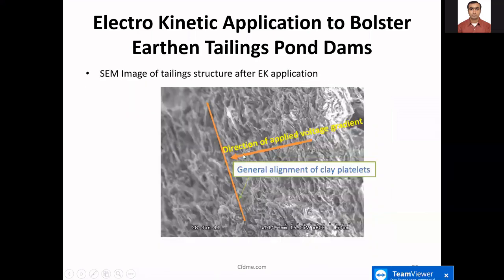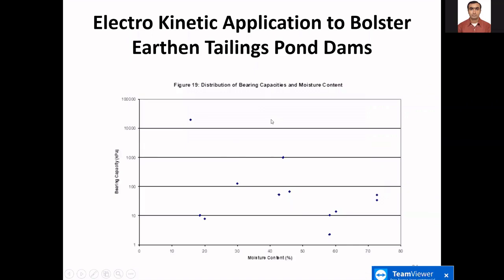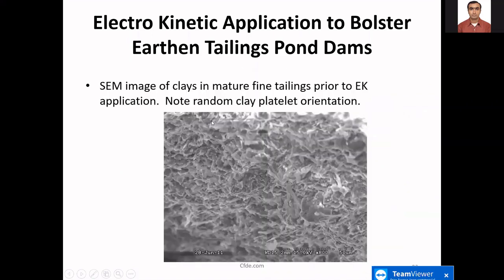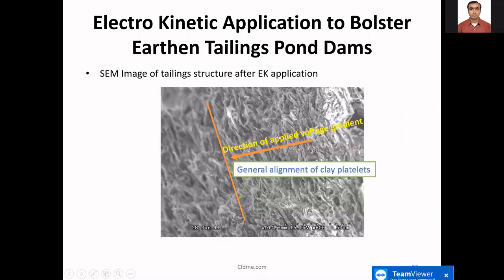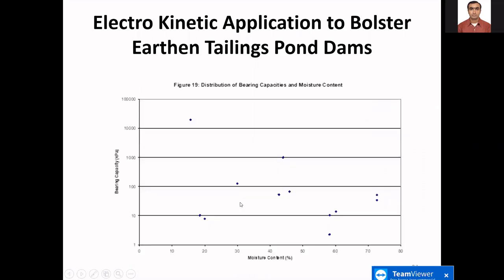So perpendicular to the direction of the applied voltage. So this is the pattern, or at least up here, it was lined up pretty well with the platelets here, but it of course was not consistent throughout, and neither was that the goal. This graph shows you the bearing capacity in kPa versus moisture content, or actually the other way around, moisture content to kPa to bearing capacity.